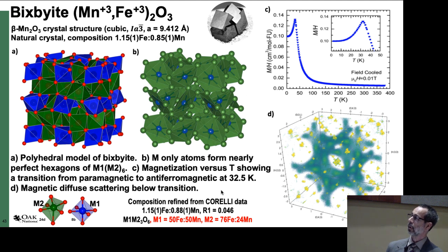Well, I should restate that. We don't know what full range of solid solution occurs in nature, but we have several crystals with different iron manganese compositions. If you just look at the magnetic ions, they form these hexagons where the M2 site's in the middle and M1's around the outside. Actually, it's the other way around, yeah. And this has all the properties for geometric frustration, and the magnetization density at low temperature shows an antiferromagnetic transition around 32 Kelvin.